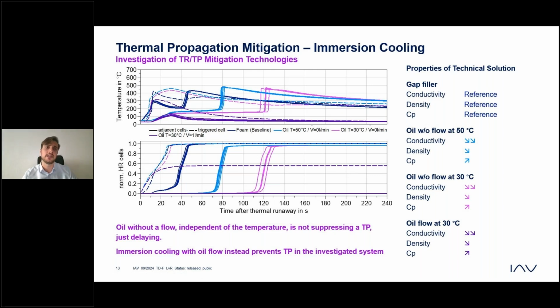But what we see here is that the adjacent cells are going into thermal runaway almost simultaneously. So we don't have this delayed propagation where one neighboring cell is seeing the runaway first, then another cell. If the oil is a bit cooler, we see that the delay is even stronger. So here we went from 50 degrees centigrade to 30 degrees centigrade, where we then have a delay of this thermal propagation. And then in another case, these purple curves over here, if we add even a velocity to this oil, then in our case, we didn't see any propagation. So immersion cooling could be another procedure to avoid thermal propagation.